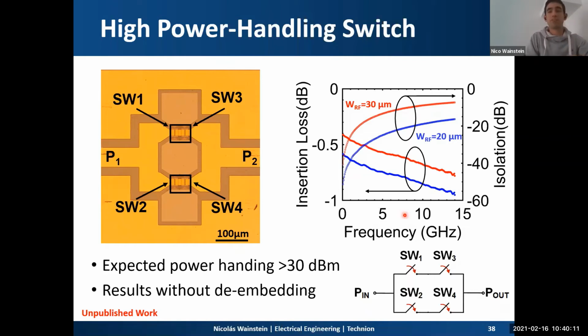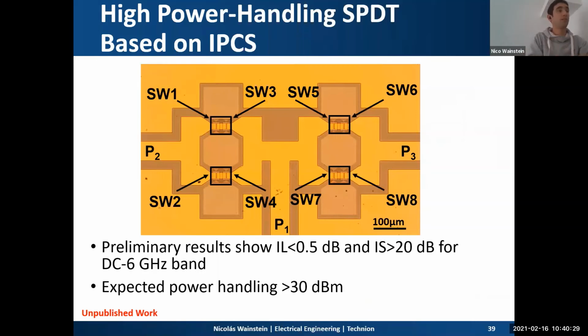So here you can see some preliminary results of a single pole, single throw device. This is a single switch. You can see that the results are pretty promising and exciting, and we expect a power handling above 30 dBm. We used this idea to build a single pole double throw, a multiplexer, with the series shunt quad configuration. That's how we call it. And this SPDT is intended to be used as a transmission SPDT for DC to 6 gigahertz radar applications. Here we also expect a power handling larger than 30 dBm, maybe a little bit higher, 36 dBm, but we will see.